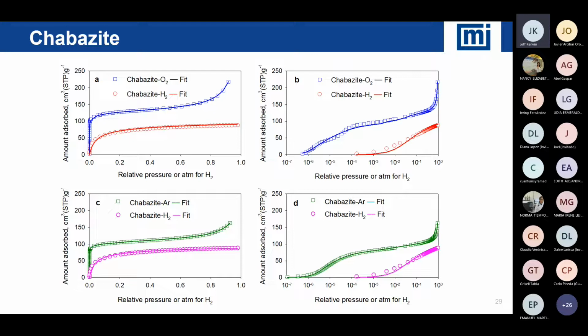The main driver for this in the application space were materials like chabazite. Chabazite over the past decade has become very significant for environmental applications, and particularly diesel exhaust abatement. So using chabazite with copper for the SCR reaction to remove NOx. Okay, so really important to clean up diesel emissions. Chabazite is the ideal material, and chabazite is ideal because it allows researchers to precisely locate copper inside of that chabazite structure, and the location of the copper is really critical for that reaction of NOx to basically nitrogen, so that we're not emitting some of these really nasty acid gases into the environment, which diesel is known for.